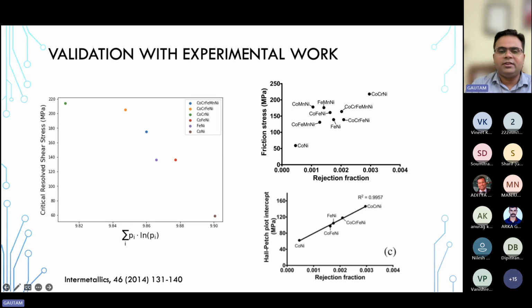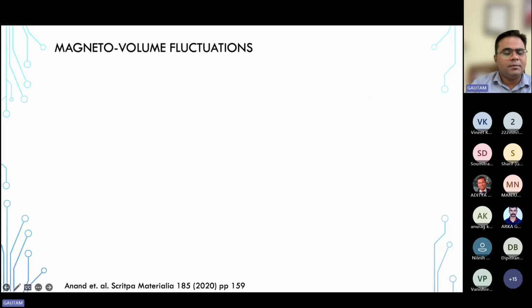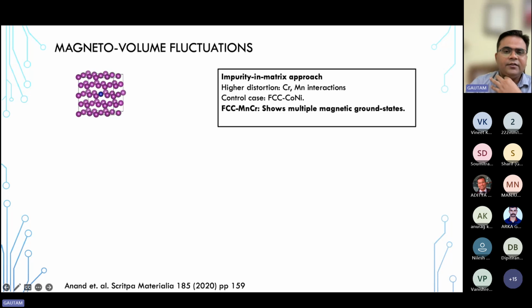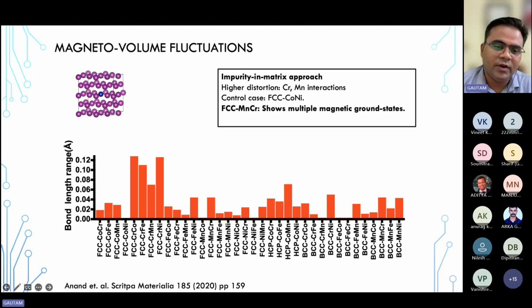When we take out the manganese, the rejection fraction shows a clear trend. So delta V values seem to be very important when we want to calculate the volume misfit. Some kind of magneto-volume fluctuations are taking place. So we carried out large-scale density functional calculations with the impurity in matrix approach. You have a matrix and you put another element there. Cobalt, chromium, iron, manganese, nickel, all these elements we can take, and instead of doing the full alloy in one go, we started with an impurity, in FCC form and in their ground state structure, adding another element as an impurity.